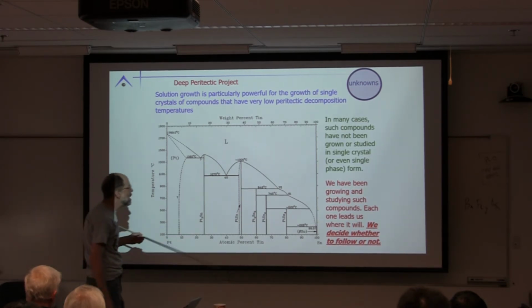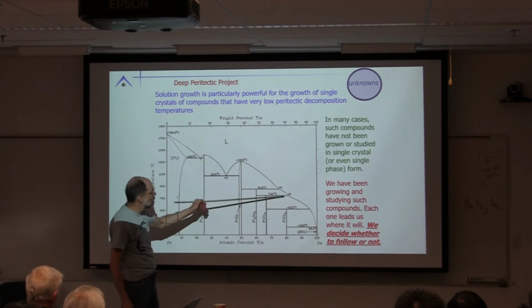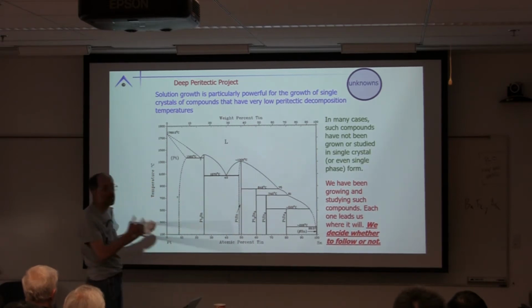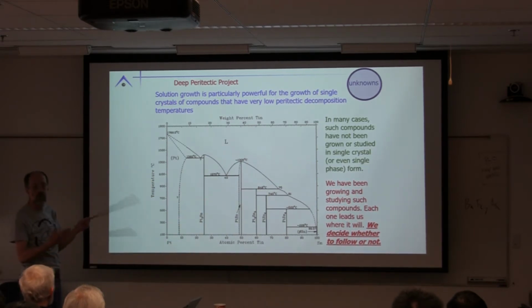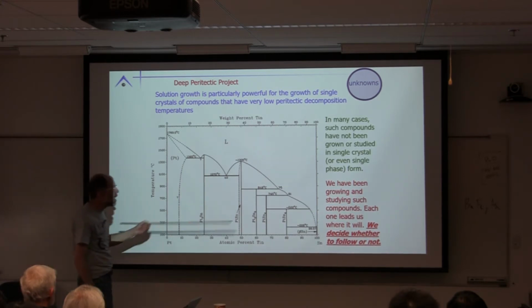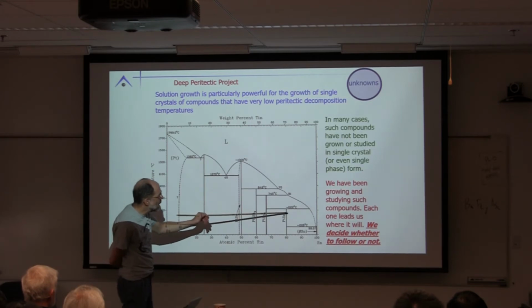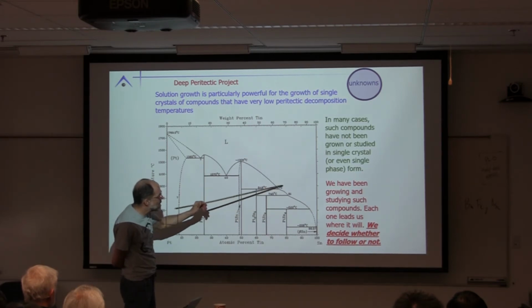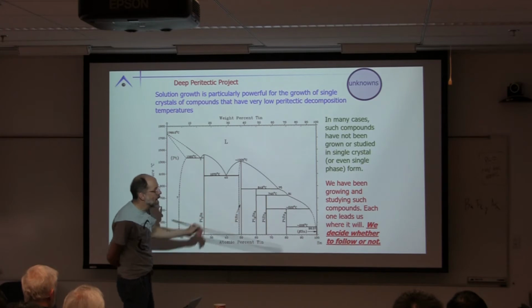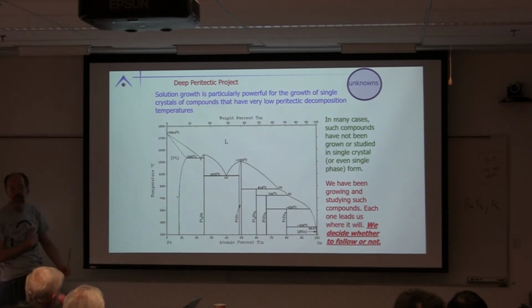Deep peritectic for me is a compound that has several other compounds on top of it and could only be grown in single crystal form, probably by solution growth. Okay? So if you look at phase diagrams and find, for example, platinum tin 4, this is probably something that hasn't been looked at in single crystal form, and probably, if it has been, it's by one of my former students or someone else doing solution growth. So this is sort of an entertaining way of saying, look, these are known compounds, and probably there's not a lot known about their single-phase high-purity properties.